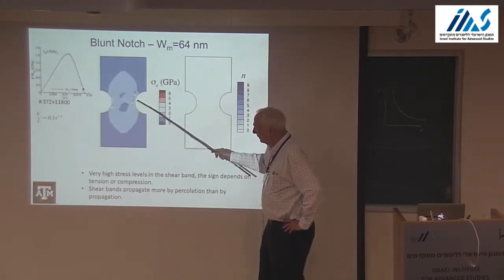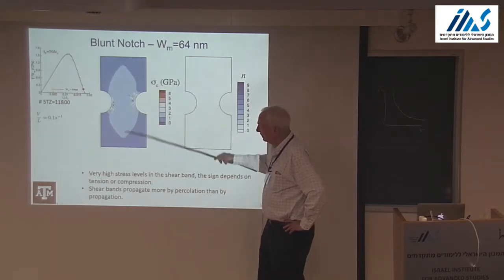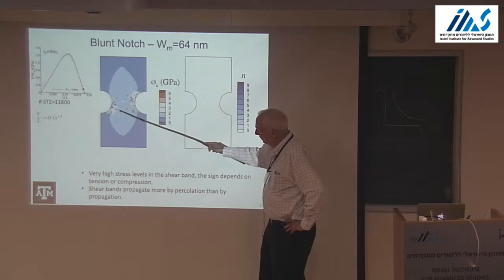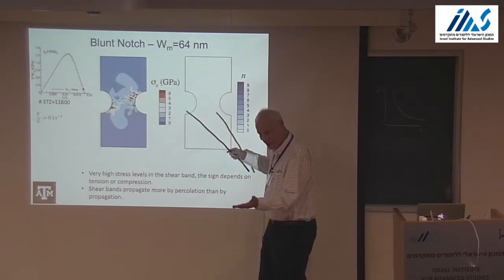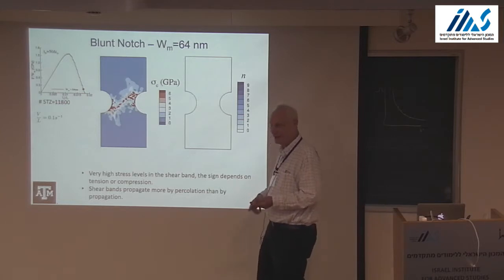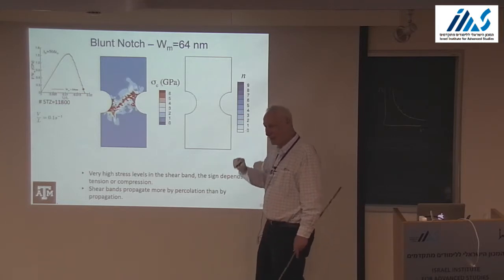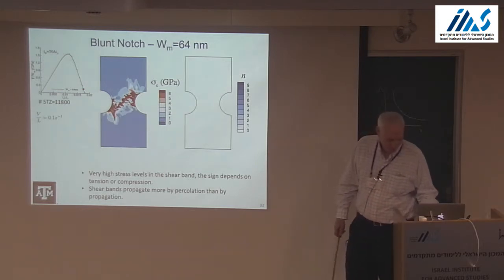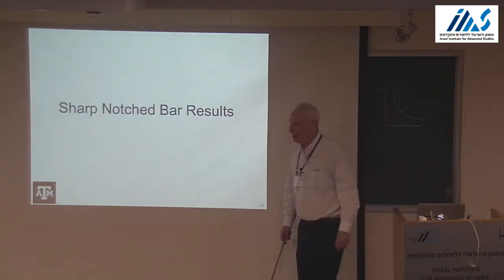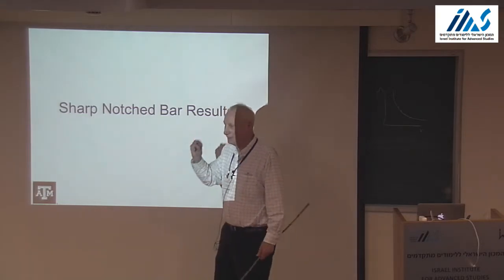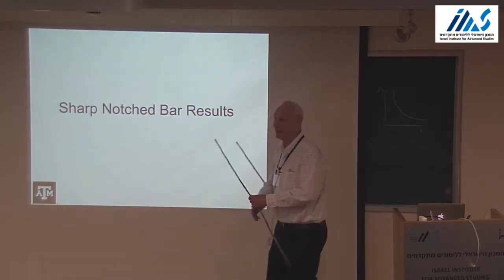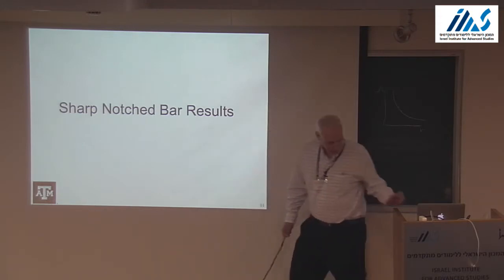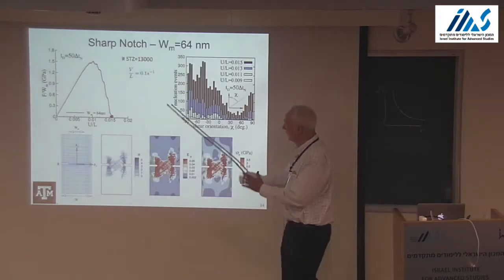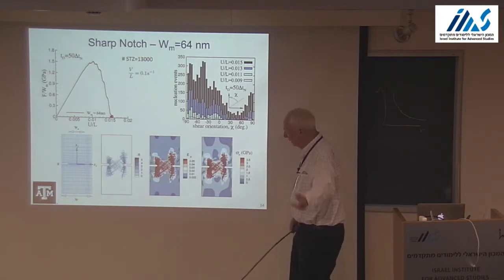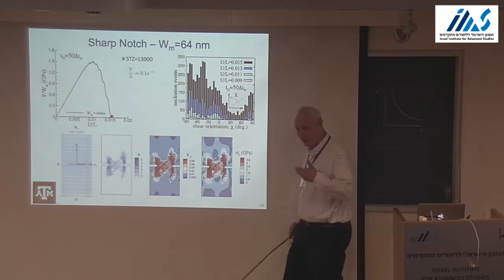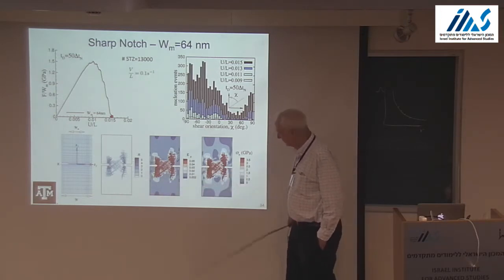This is elastic. You begin to get some nucleation. Stresses increase. Then as the band forms, the stress comes in. You get unloading associated with the shear band. But again, it doesn't propagate, it percolates, more or less. Yeah, they're blobs of activation, boom, boom, boom, because of the interaction, exactly. And then the blobs link up, exactly. So just one more thing, sharp notches. Again, the orientation spreads out. The shear band pattern differs. A lot more activation occurs.